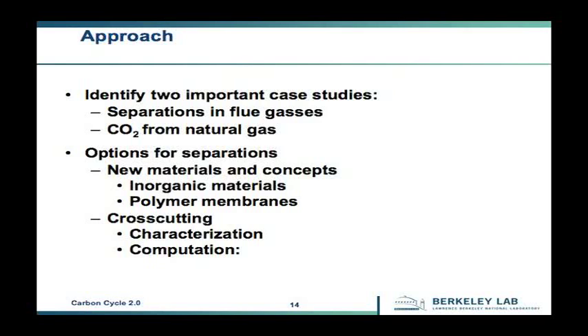One is a separation from flue gases, as I have discussed. The other important separation problem of CO2 is in natural gas. Some of the gas fields actually may contain as much as 70% CO2. For example, there are several very large fields in Australia, and they are not giving permission to explore those fields if the CO2 is not put back into the ground. Well, if you need this enormous amount of parasitic energy, you need to burn more methane to do the separation than you will ever get out of it. So the exploration, if you cannot do this separation, is not very productive.